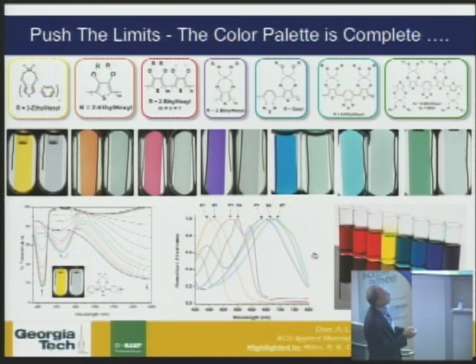And you can see the pure dioxythiophene, you can see copolymers with relatively electron-neutral systems like phenylenes, and then donor-acceptor systems with things like benzothiazole here. And what's important about these polymers is that they are switching from a vibrant color state. This is a film that's been spray-coated onto an electrode sitting in a cuvette. You can see the counter electrode and the reference electrode sitting here. And they oxidize into a highly transmissive state.